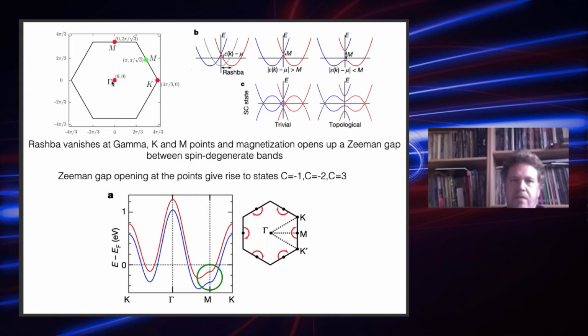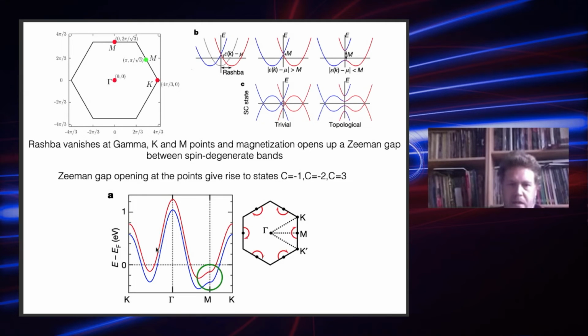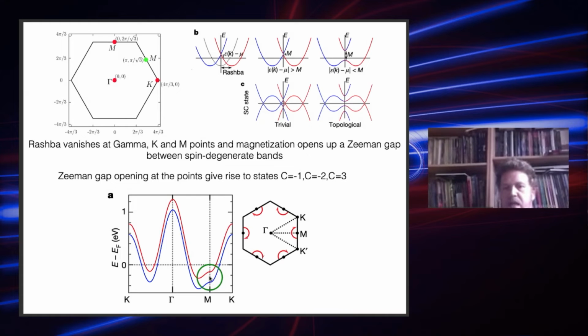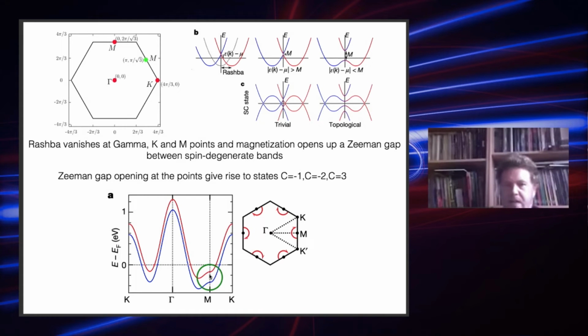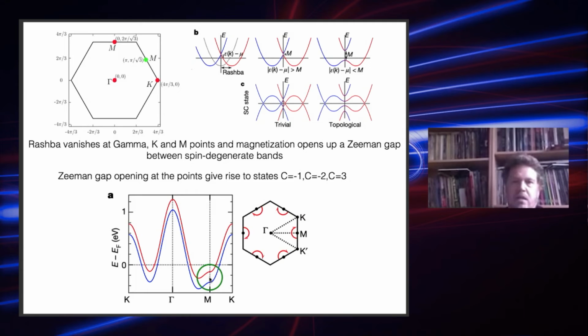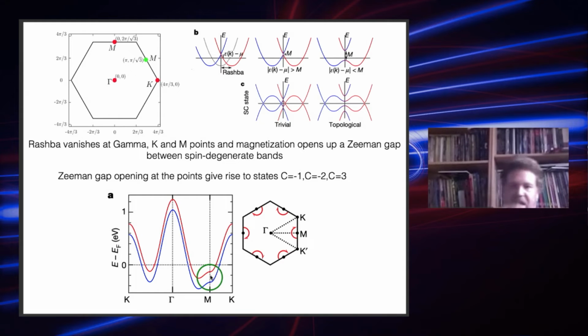Right. So now we have three points where this topological gap is opening up, and we can see in the band structure schematics that our high symmetry points are here, and the pristine Fermi energy would be somewhere here. So we see that the topological gap opening near the M point is closest to the Fermi level. So the two other high symmetry points are much further away from the Fermi level. So it is reasonable to assume that if there is topological superconductivity in this system, it is somehow related to this M point and the topological gap opening at the M point.